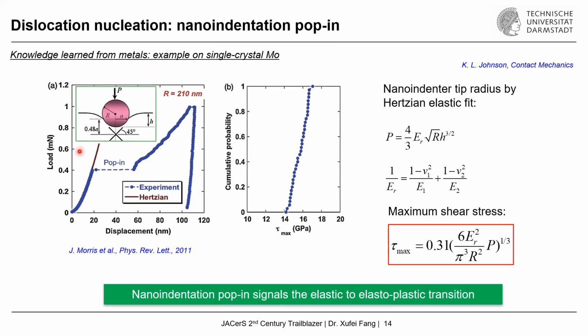So here is one representative curve from the nano-indentation test, where you can see in the y-axis, you have the load recorded. In the x-axis, you have the displacement recorded. So simply put, you are just pressing a very sharp indenter into your material, where your machine is able to record the load and displacement simultaneously. So imagine that you have your indenter material. Very often it's diamond pressing into your material.